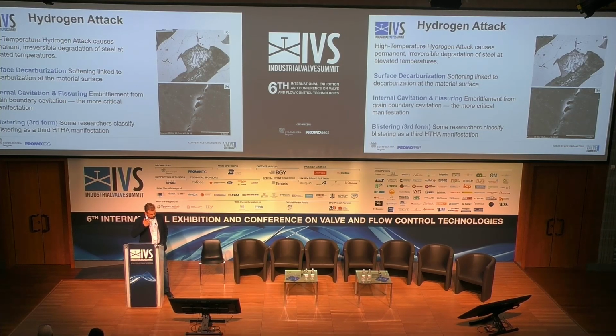The last one is the hydrogen attack, where we are talking about proper corrosion. This is the proper corrosion mechanism, and it's only linked to high temperature hydrogen attack. It's a degradation, like it was discussed previously in the previous panel. So it's a chemical attack on top of the surface, and you're noticing the typical signs of corrosion.